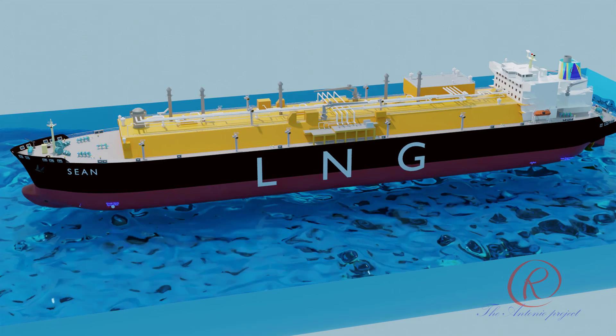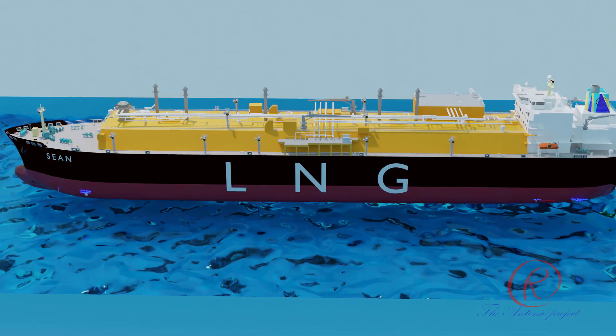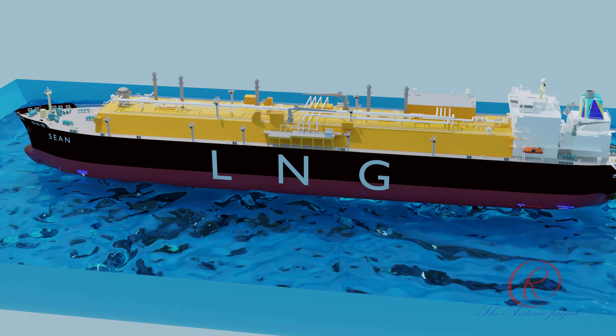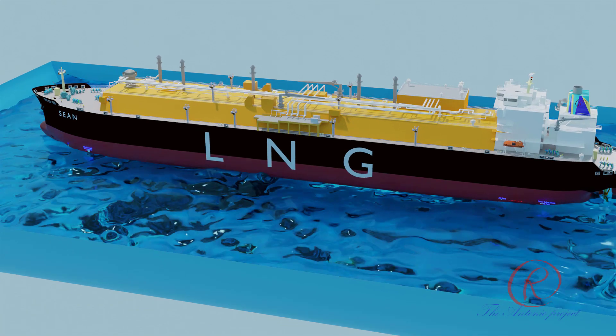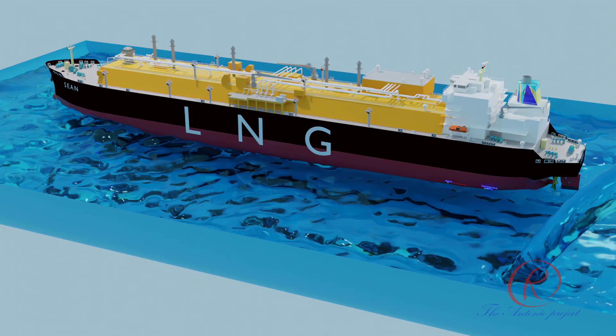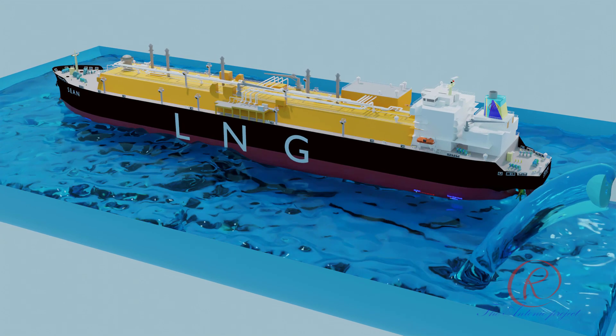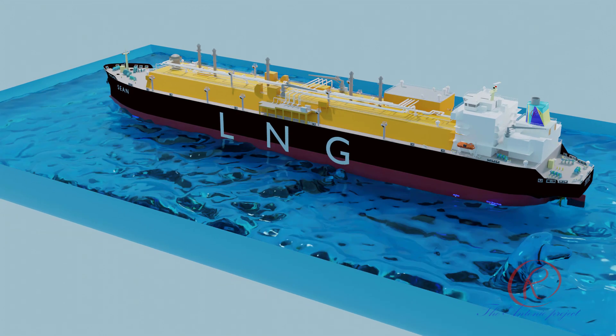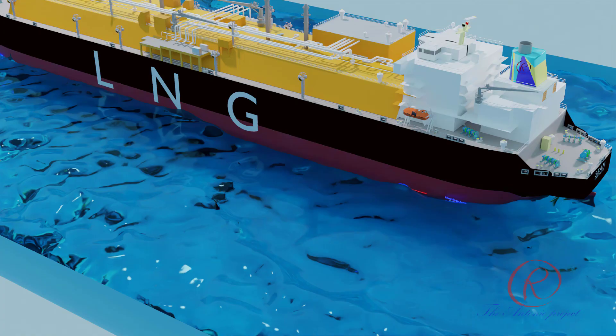Freshwater passage: when a ship moves from sea water to fresh water, its electrical conductivity reduces and its resistivity increases. Because of reduced conductivity, the reference cells will not be able to detect a potential difference. It is important to limit the output protective current from the impressed current anode manually. When in automatic control, the ICCP will increase its rectifier voltage to maximum, so with manual control it is necessary to limit the impressed current and avoid over-protection and damage to the hull. At terminals, when the ship's ICCP is switched on, it will try to protect the jetty as well by increasing the current in the system, and this can lead to overload. Hence, the ICCP power source is always switched off in port. Circular and strip anodes emit electrical current into the water surrounding the ship. The current flows through the water by ionic conduction and is subsequently delivered back to the power source through the reference cell and systems controller.